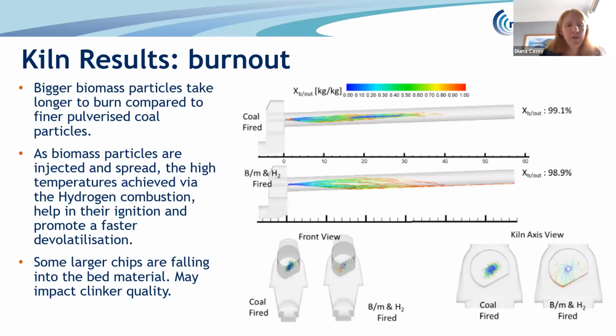So starting with the kiln, this diagram showing the burnout or how well the fuel combusts. So this diagram at the top is the baseline scenario with 100% coal. And now it's worth remembering that these kilns and the calciners are effectively designed around the use of coal. So these show what we're sort of trying to achieve. So in this case, we've got a nice long flame in the centre of the kiln that's not touching the edge in any way. Well, it's probably hard to see, it's quite small, but it's not touching the edge.